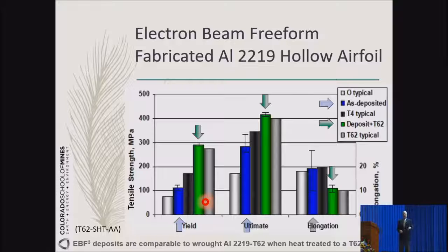I said, well, you can have this part built 3D and then HIP it, hot isostatic pressing, for example, and then heat treat it, you will develop the property. So this slide here tells us a little bit about that. The blue one is the as-printed. They are pretty lousy compared to the one that is deposited plus T62 processing, which is heat treated.